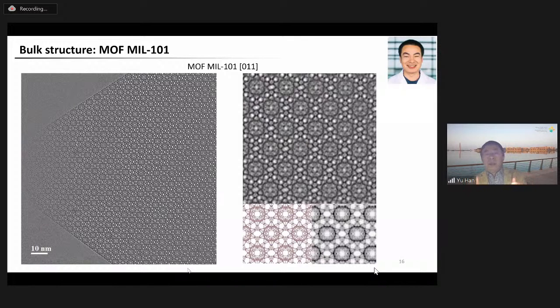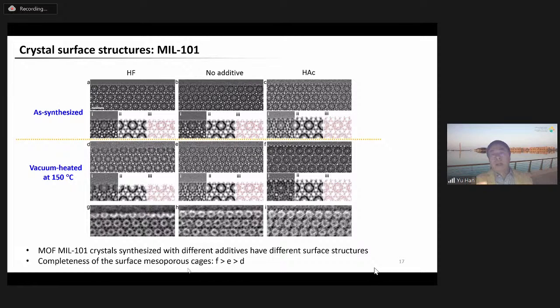So then we studied three MIL-101 samples that were synthesized with different additives as modulators. The three modulators are HF, acetic acid, and no modulator, three different synthetic systems. It's known that the modulator can influence the crystallinity of MOFs and their crystal size, but no one knows that the modulator also has influence on the surface structure of MOFs, because before, it was not possible to probe the surface structure. But now we can look at the surface of the crystals synthesized from different systems with HRTEM.